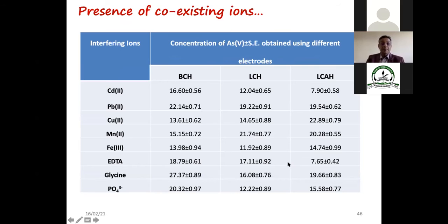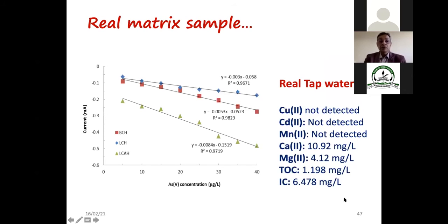Then we looked at the presence of different coexisting ions, and we got the data for cadmium, lead, copper and others. Again here the copper was interfering. And we also tried a real matrix sample. That means we took simple tap water and analyzed what is present there. We observed that the inorganic carbon is very high here, and the calcium content is also very high.